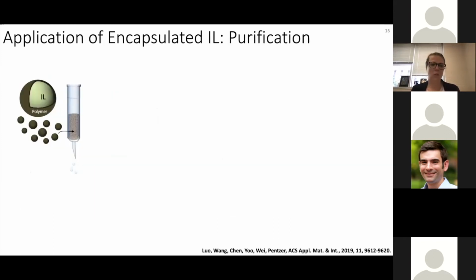And so we use these for a number of different applications. And in all instances here, we're relying on the fact that the shell is permeable to small molecules, which is interesting in its own right, because normally if you put nanosheets in a polymer, what ends up happening is you decrease the permeability. But in this case, we're actually seeing really good permeability.